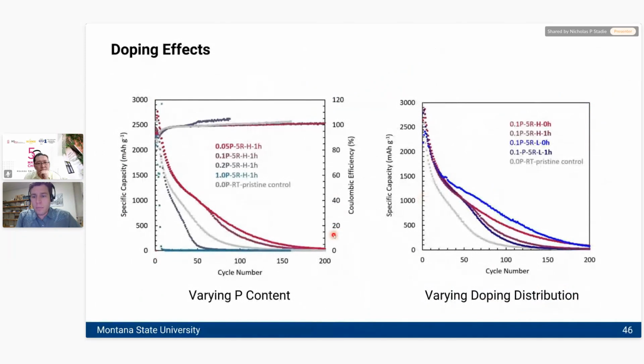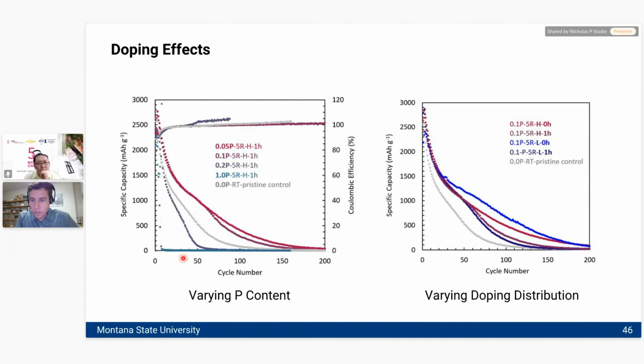On the left, now these are non-optimized cells, so they are fading pretty fast, but we're seeing capacity as a function of cycle number depending on the concentration of phosphorus in the lattice. As we go from low phosphorus loading to high, and we compare that to the control, which has 0% phosphorus, with initial concentrations up to maybe 0.05, 0.1, 0.2, and then even at just one, sorry, these are atomic percent numbers, you already make massive disruptions to your silicon lattice, making it completely ineffective as a lithiation anode material. This is an interesting set of data that we published 2 years ago now.